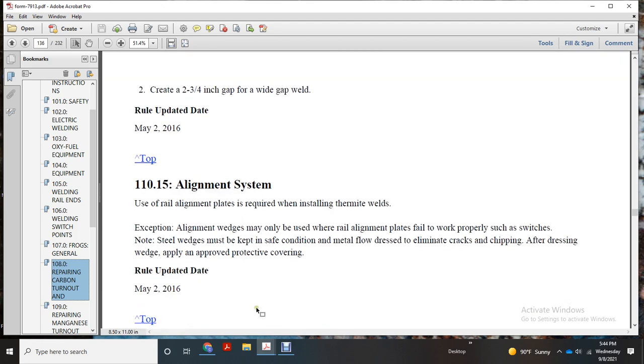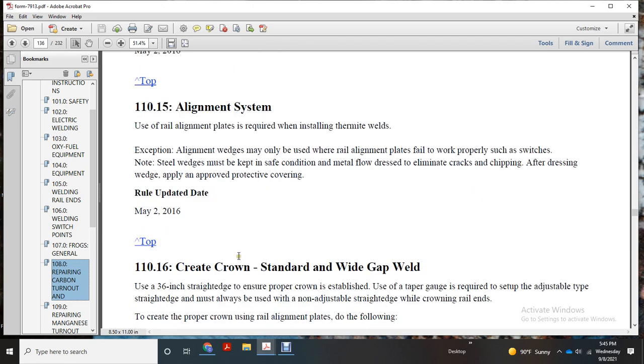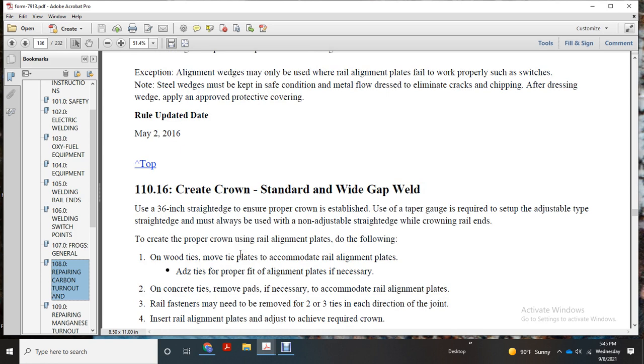Alignment system. Use the rail alignment plate with the installed thermite weld, with one exemption. Alignment wedges may only be used where rail alignment plates fail to work properly, such as switches. Note: steel wedges must be kept in safe condition. Metal flow: to eliminate cracks and chipping, apply the dressing wedge with a protective covering. Creating a crown for a standard and wide gap weld.